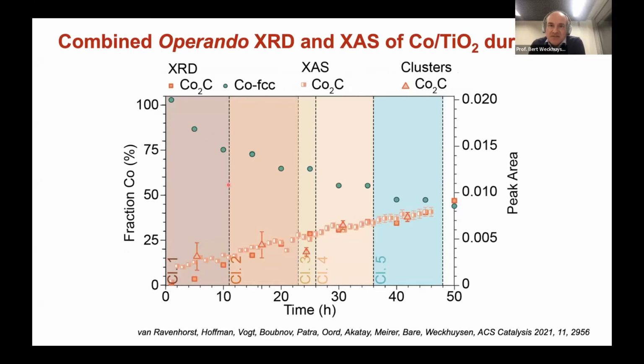If you bring now these different results together, X-ray diffraction and XAS, what you see is that you have a gradual buildup of this carbide, a gradual drop of the cobalt FCC, and that you have different contributions of these, and you can measure them both by this cluster approach or by this reference approach. Important is that the carbide formation does not correlate with activity. In other words, it's not that the carbide is related to activity, so that remains still this cobalt metal phase, which is suggested.